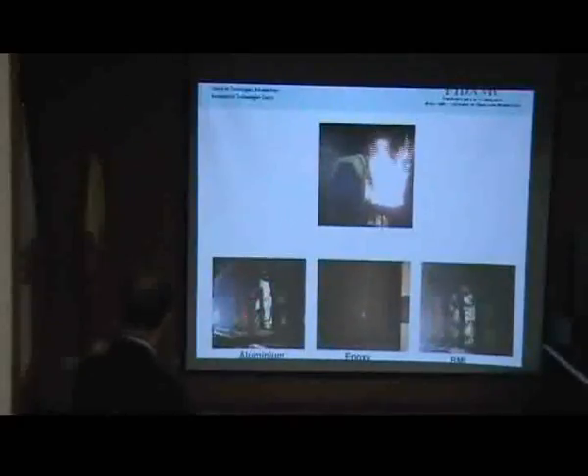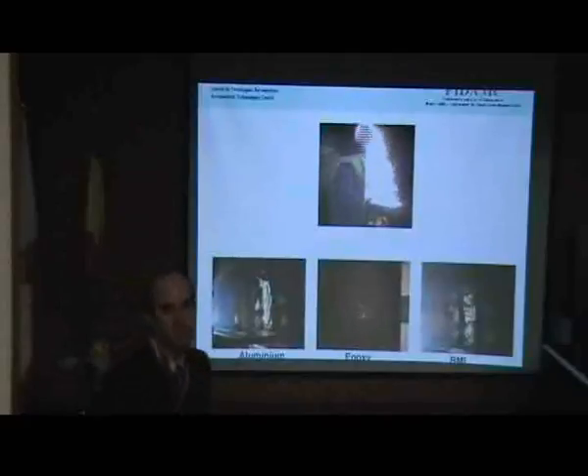At 2 minutes and a half, the aluminum starts to melt, and when the aluminum fuselage melts, the flame penetrates inside the cabin, and the smoke generated in the kerosene combustion also penetrates. And it's quite clear the difference between the epoxy resin fiber composite and the BMI. So here is the fire penetration in the aluminum fuselage, and all the smoke generated in the kerosene combustion enters. After 3 minutes of the test, we extinguish the flame. It's quite clear the difference in the smoke concentration between the three different materials.